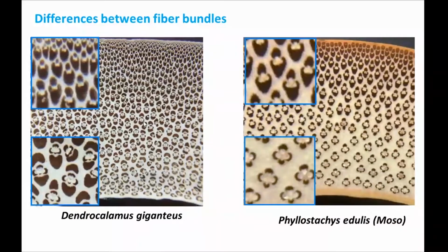And here we can see exactly in the top of the bamboo, in the external wall of the bamboo, the high concentration of the fibers. In the lower part or internal part of the bamboo, you can see matrix or parenchyma. The concentration of the parenchyma is more. And in the Phyllostachys edulis also you can see exactly the fibers, the matrix, and here more concentration of the fibers at the external part.